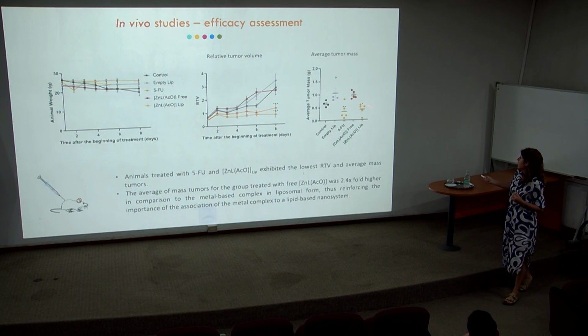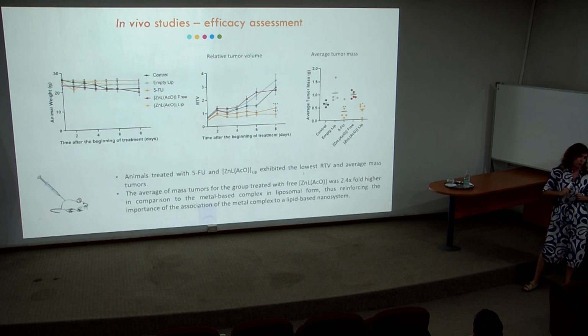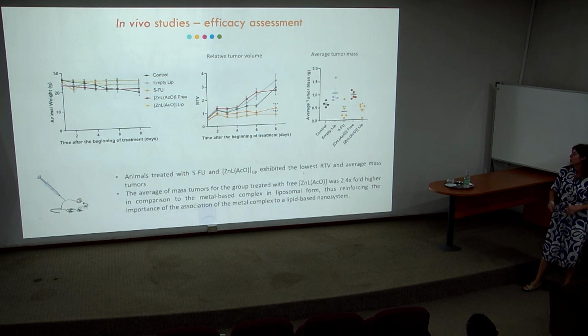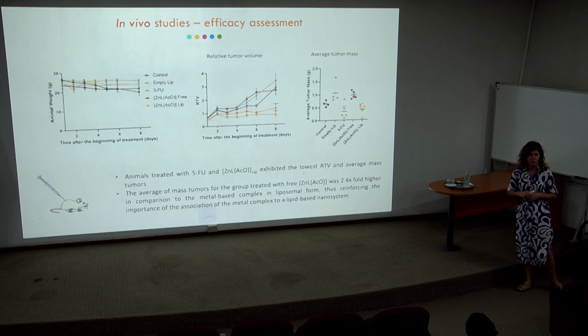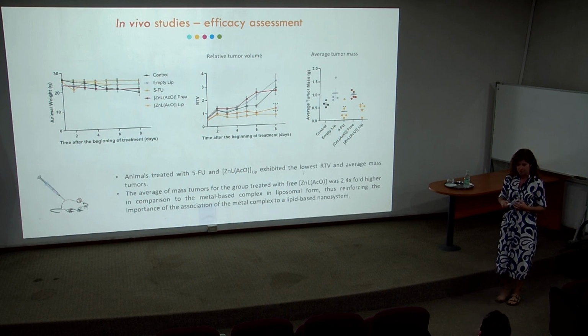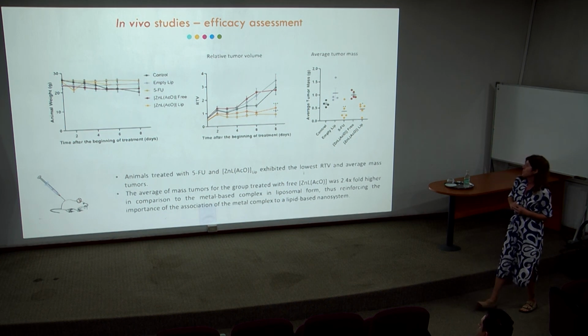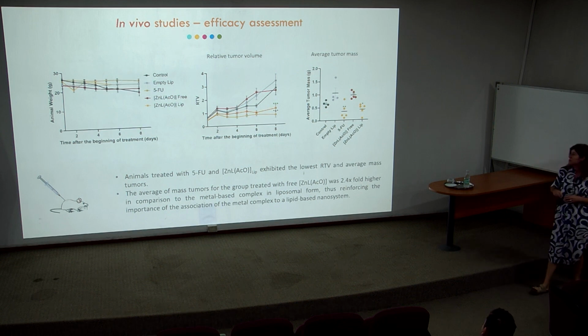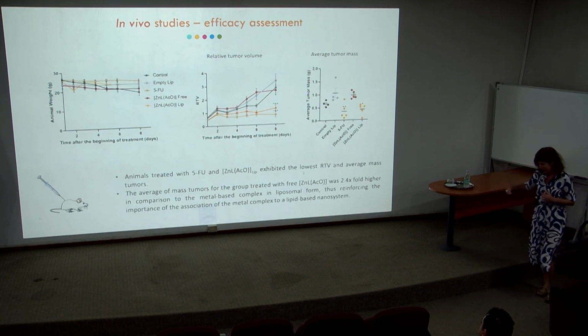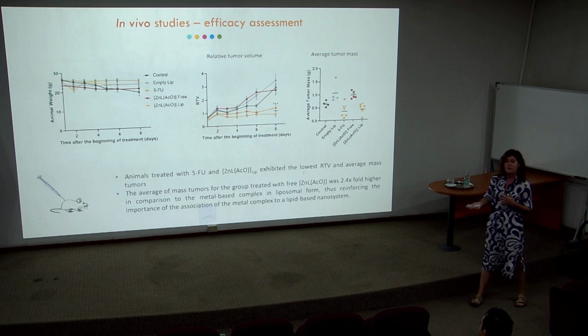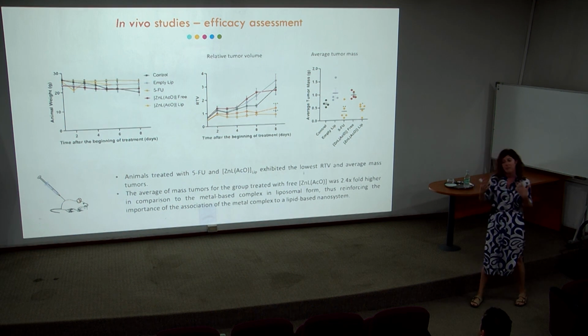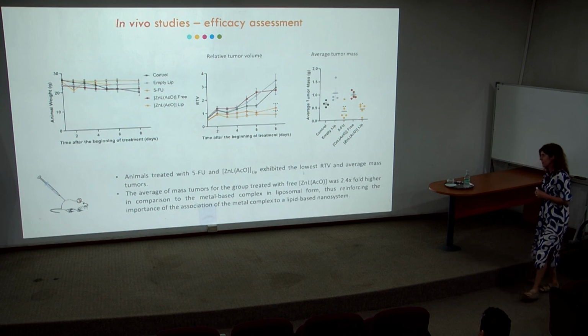And if we compare the results with the positive controls, we use a much lower dose, 3 times lower, to have more or less the same effect. So this was a positive result. We still did not proceed further with this system. We also studied the other metal complexes. We had interesting results with the ruthenium complex.